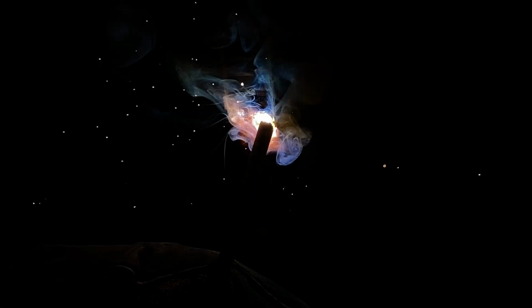As you can see, we've left the edge in place from that previous flushing run, which makes that line of weld clearly visible, which gives us a lovely guide to follow and helps ensure that that capping run stays straight up either edge. So we're running the same amperage as before, we're running 110 amps. The only difference in technique now is we need to make sure the capping run sits slightly over flush, giving us that reinforcement without cutting into the sides of the plate. To achieve that, we'll just pause a little bit longer on each side before moving across the run.